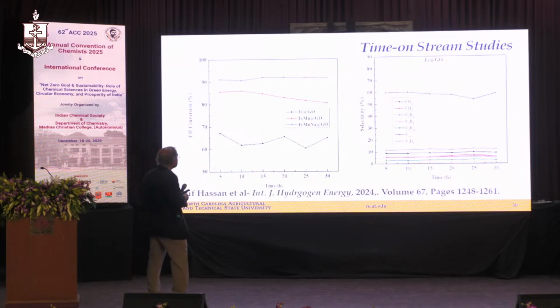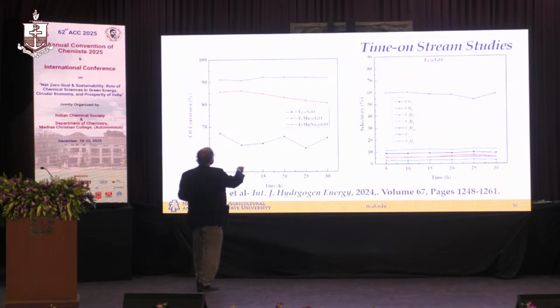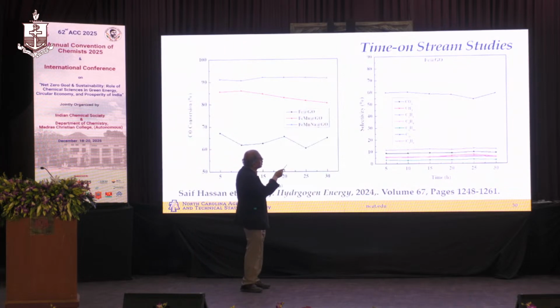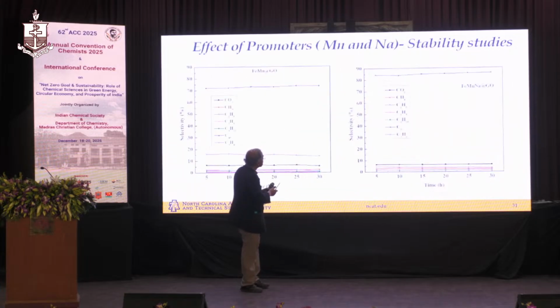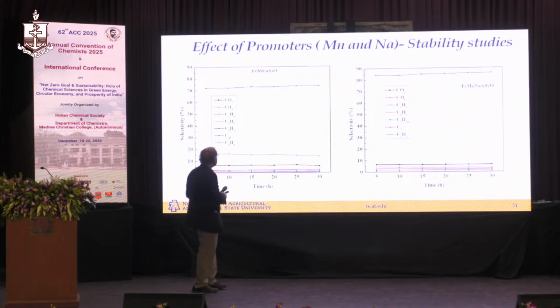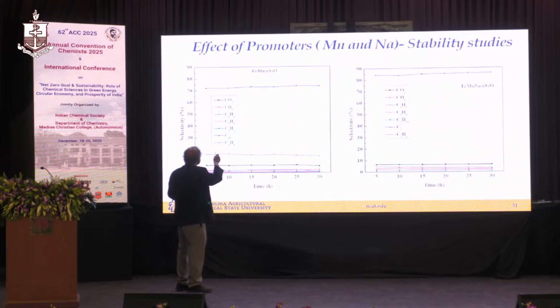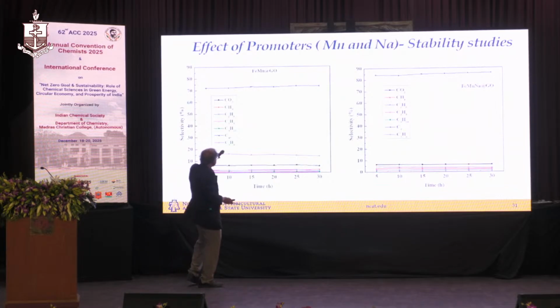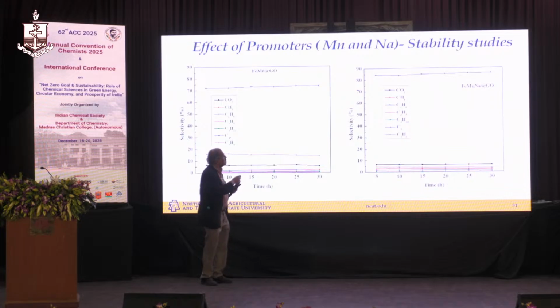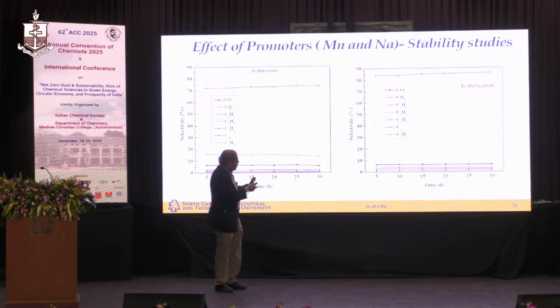Yeah, and so you see here, manganese sodium, the conversion goes up, and then this is the iron graphene oxide, and you can really move through this, and then you can see the other products, the selectivity to the C4 plus. The C4 plus means all the other higher hydrocarbons. So those go up with the promoters, as you can see with the manganese sodium.